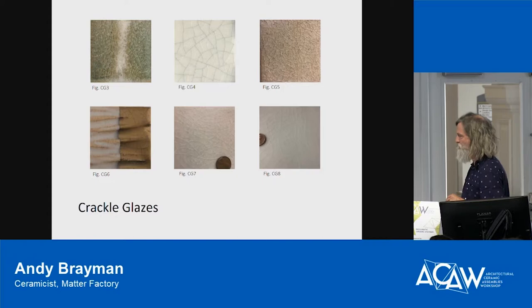And as people who know so much about architecture, and especially older buildings, you'll know if you see an older terracotta building in Manhattan that you can see the crackle effect on the surface. It's often the pollution that gets into that surface and causes it to darken along those lines. There probably are ways to clean it, but typically that's just the way it is and that's the way it stays. Some people love it so much that they'll actually stain the work right after the crackle. I think Boston Valley's done this for clients before, where it'll come out, it'll crackle, and you can stain it with a pigment that'll go in and stay there and speed that process up and amplify the look of that crackle.